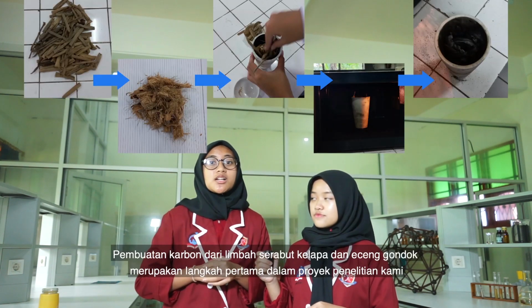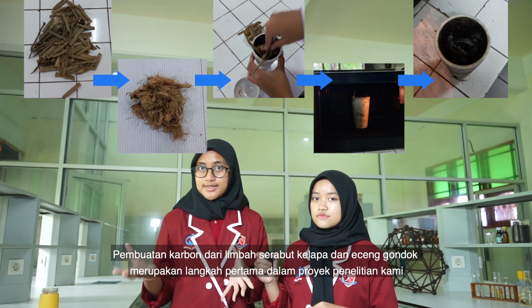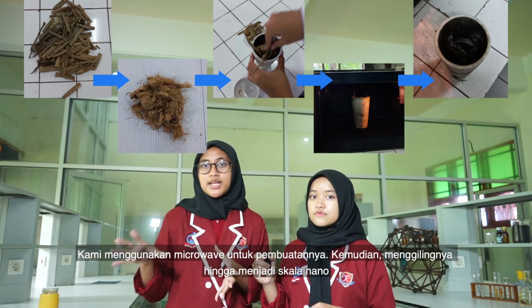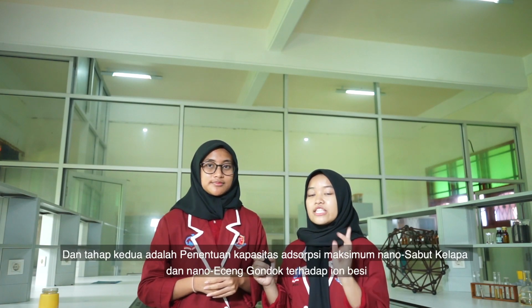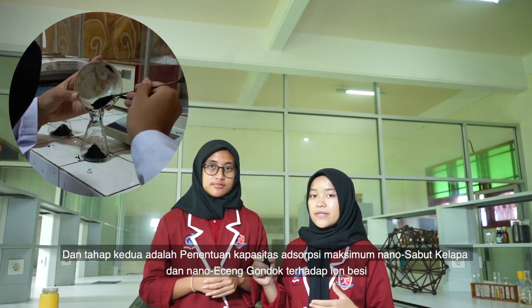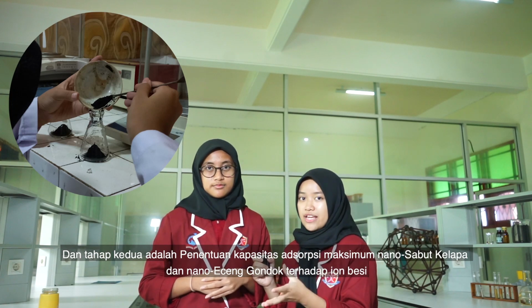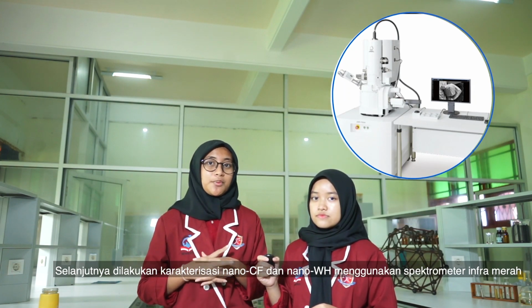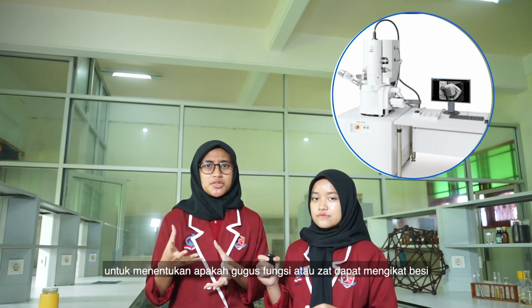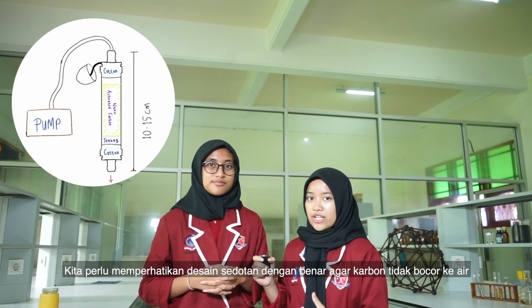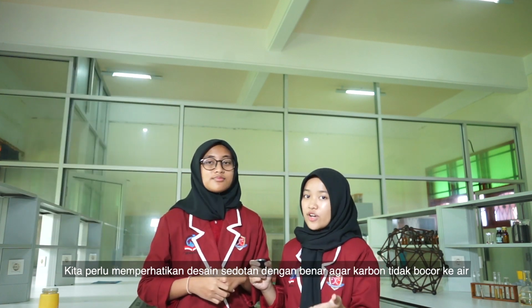Next, we're going to explain about the research procedure. The first one is making carbon from coconut fiber waste and water hyacinth, and then we use a microwave to make it, then grinding it into nanoscale. The second step is the determination of maximum adsorption capacity of nano coconut fiber and nano water hyacinth to iron ions. Next, we characterize the nano coconut fiber and nano water hyacinth using infrared spectrophotometers to determine whether the functional groups or substances can attach iron or not. And the last step is to design the straws. We need to pay attention to the straw design correctly so the carbon does not leak into the water.